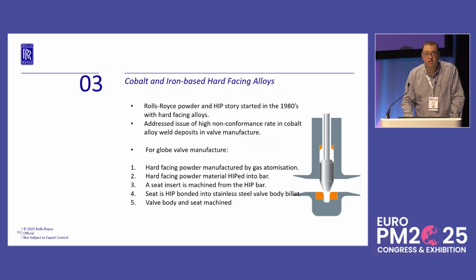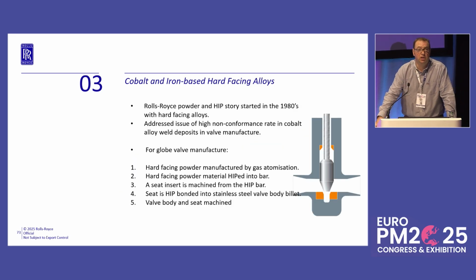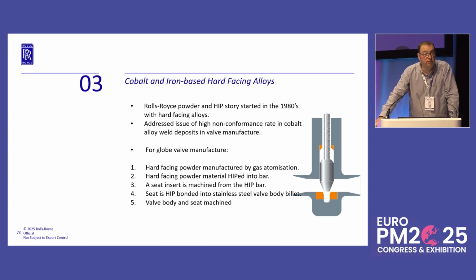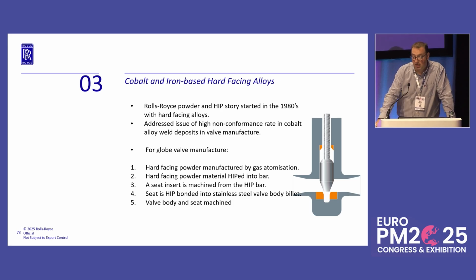So our story starts well over 40 years ago in the early 1980s with a problem in manufacturing. Manufacturing issues is actually one of the undercurrent themes through the rest of the talk today. What we had was a problem where the welders were struggling to deposit a cobalt-based wear coating down the bottom of those bores. The non-conformance rates were very high, well above 50%, and really causing the business a lot of problems. So they looked for an alternative manufacturing means. Same material, just try and get the yields up.